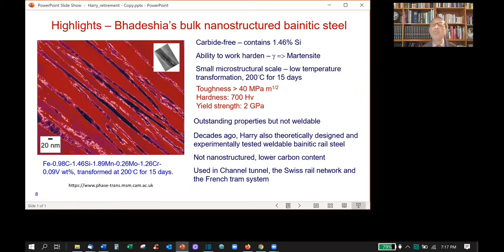I want to mention two of Harry's inventions of bainitic steels. The first one is carbide-free nanostructured bainitic steel that is made in bulk quantities, hundreds of tons. It is carbide-free because it contains about 1.5% silicon. It is designed to have the ability to work harden, with gamma to martensite transformation under stress, and the small microstructural scale is achieved by doing the austenite transformation at low temperatures. In the case of this microstructure, at 200 degrees centigrade, and it took about 15 days.